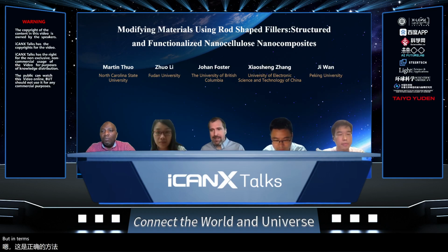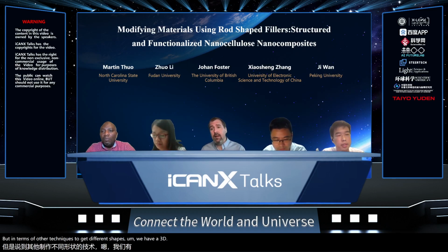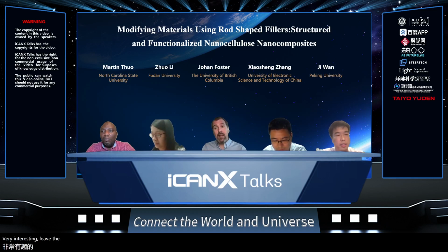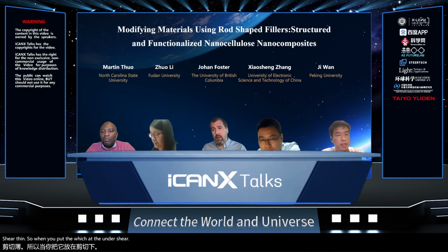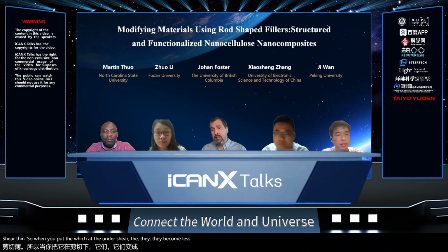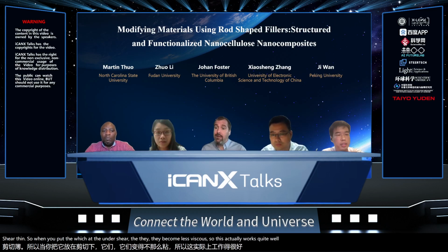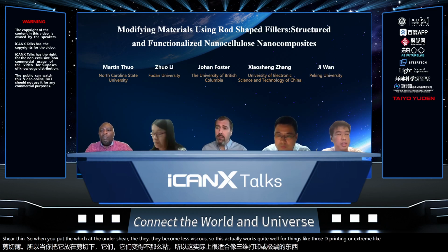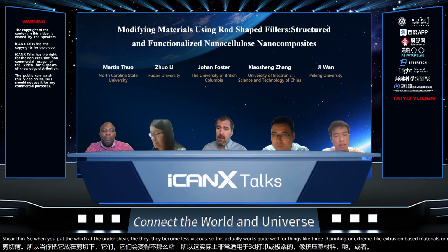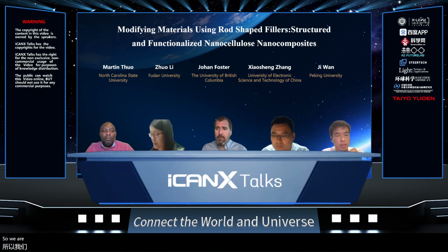But in terms of other techniques to get different shapes, we have 3D printed these adaptive materials and the composite materials. Very interestingly, the cellulose nanocrystals, because they're rod shaped, shear thin. So when you put them under shear, they become less viscous. So this actually works quite well for things like 3D printing or extrusion-based methods, right? So we are looking at other methods to make structured structures out of this.